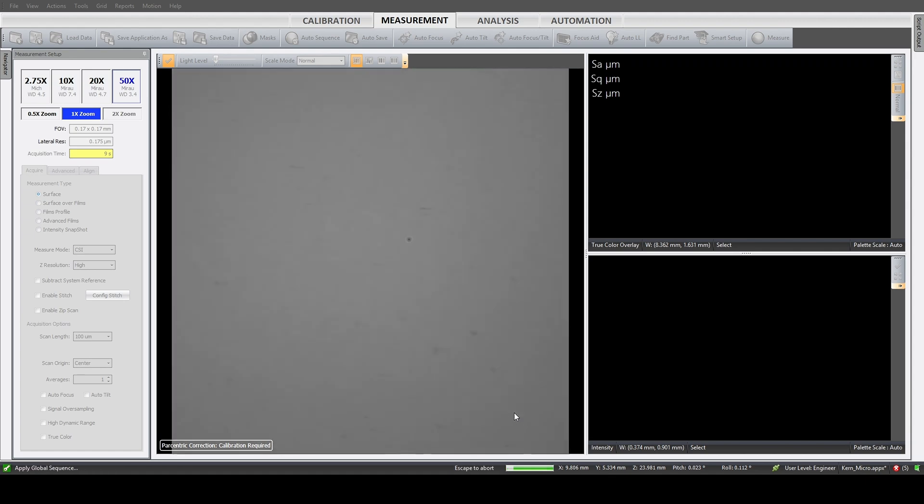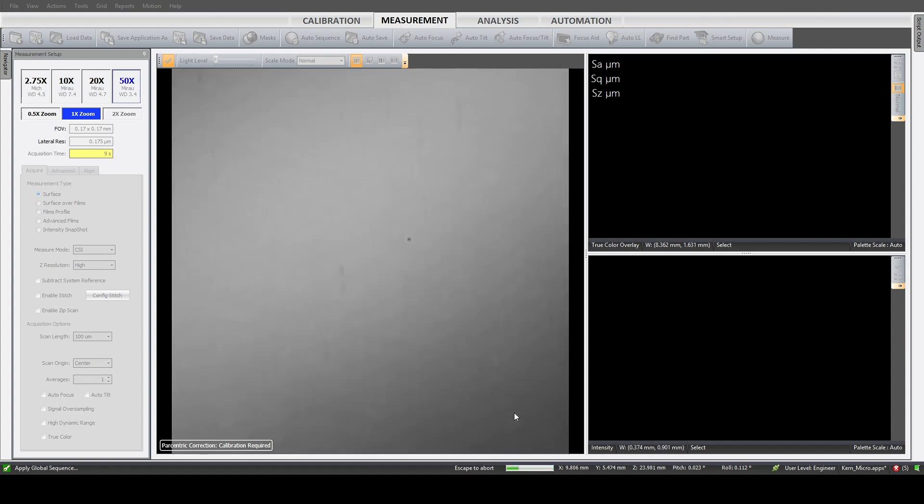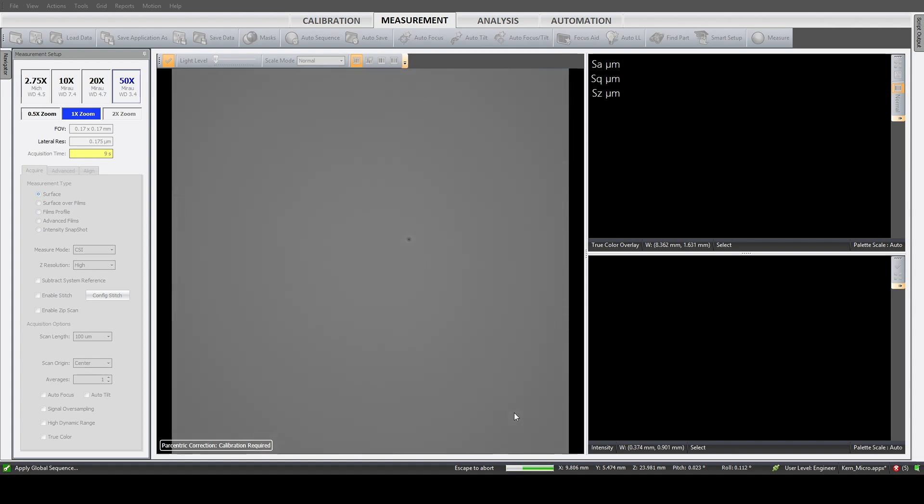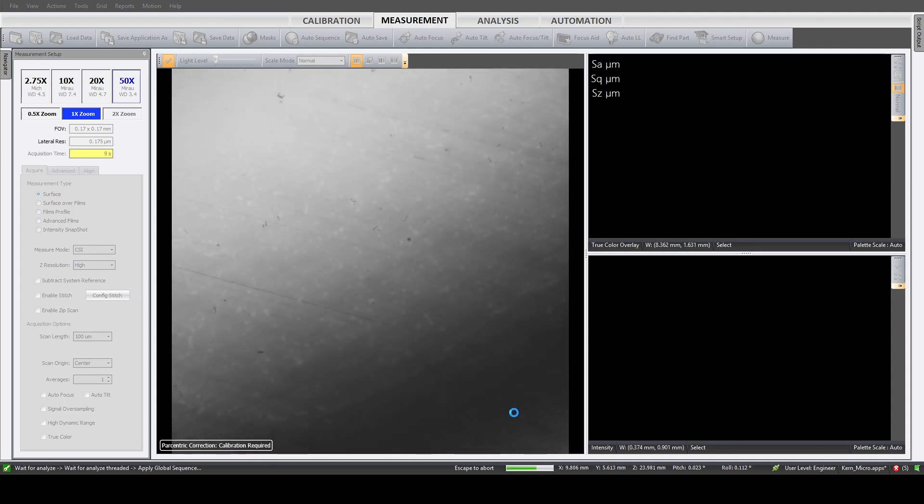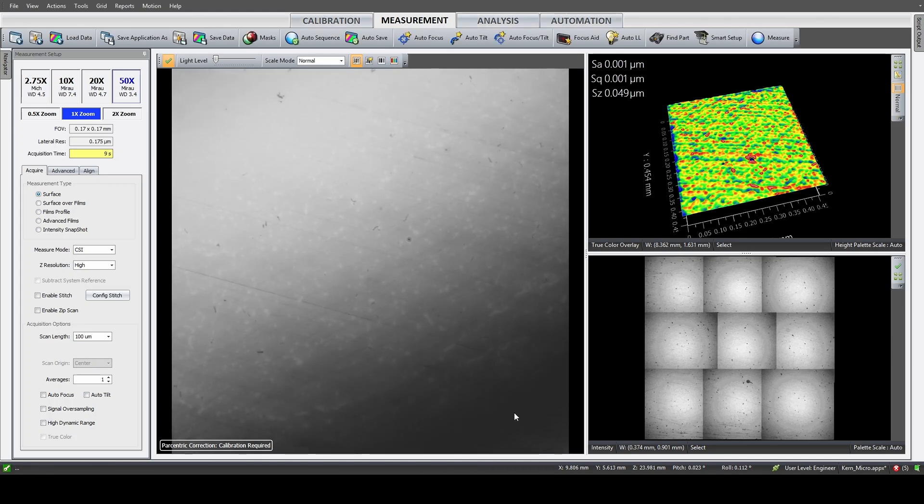And I would also say that the filter size depends on the area you're scanning. So if you, for example, record 400 microns, your filter can't be 400 microns. It always needs to be less. Otherwise, the filter is not working. Having a very small area also requires a very small filter. And this means your surface roughness is way too good. It's quite a bit of data, so stitching takes a small amount of time. And then you can see that we immediately hit like one nanometer surface roughness here. But maybe let's switch over to MountainsMap and take a closer look at the data.